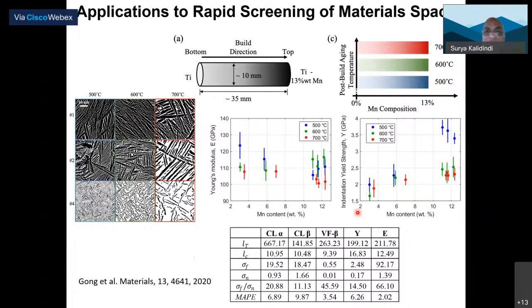Now, how do we use some of these techniques? One of the things we have done is to look at high throughput synthesis and exploration. This particular sample was made by LENS, and it has a gradient. It was made by Pete Collins at Iowa State University. Here he is getting a composition gradient from titanium at one end to titanium manganese at the other end, so you get different chemistries. Then he makes bars, and after making the bars, he is post heat treating them at 3 different temperatures. So we have 3 bars.